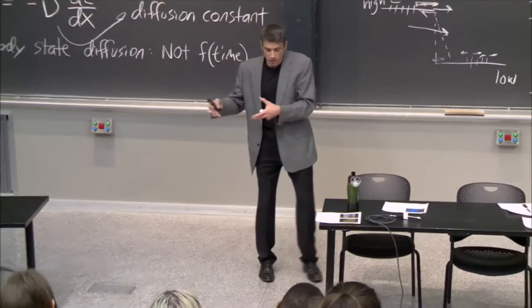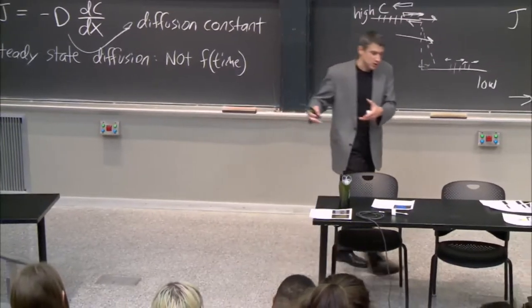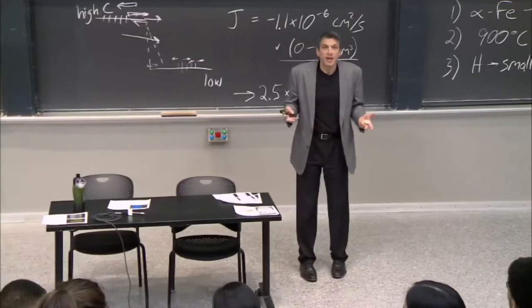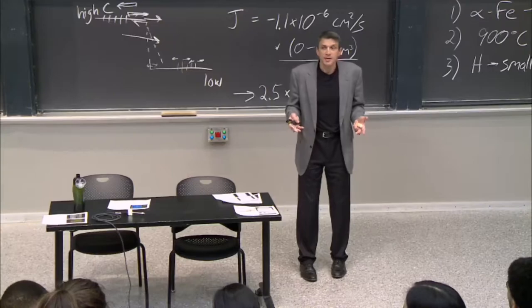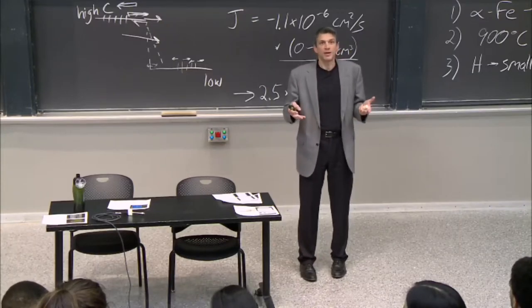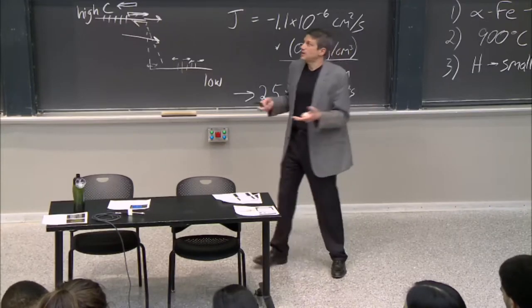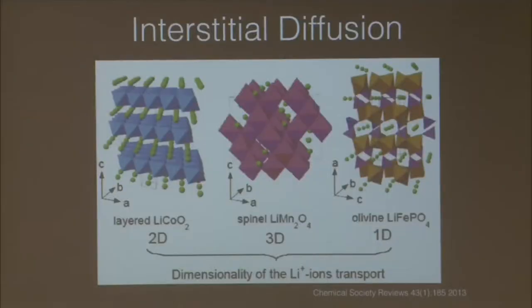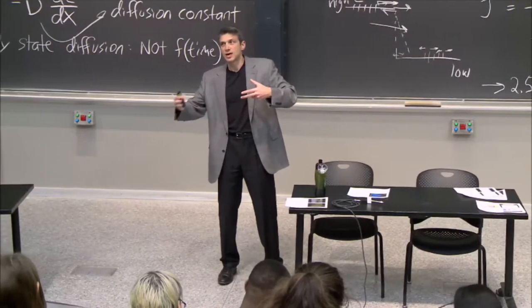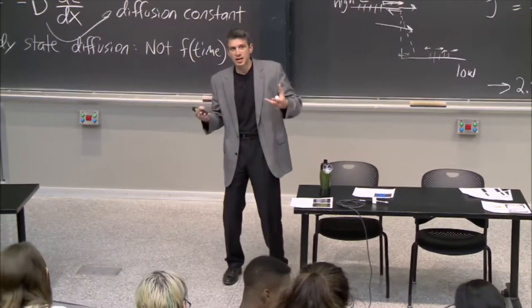And then when we charge it up, we push them back over to where they came from — that's the cathode, which is a lithium compound. But it has to be a material that can hold lithium in it, hopefully at very high concentration, but also be okay to lose it and not completely collapse.